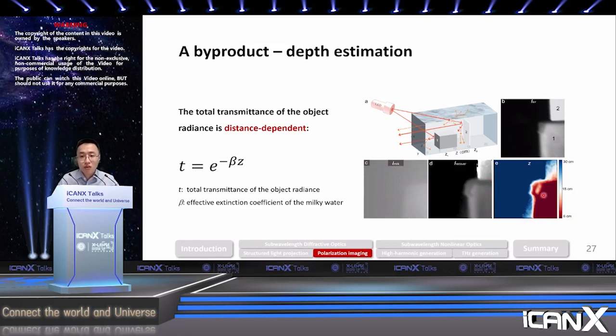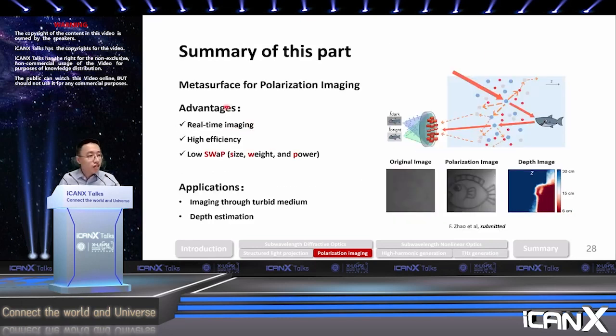To summarize this part, we need the subwavelength metalens with subwavelength meta-antennas for polarization imaging. The advantages are that we can do real-time polarization imaging, with a relatively high focusing efficiency, as we measured the diffraction efficiency, and the focusing efficiency is greater than 50%. Compared to other bulky lenses, it also has low size, weight, and power.